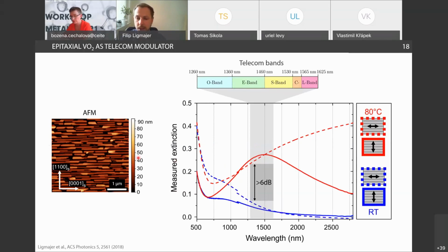And of course, as this material is anisotropic, it will be polarization sensitive. And this is exactly what you see on this graph. So again, we measured extinction by combining various detectors and light sources in an FTIR microscope and spectrometer. You see that at room temperature there is basically very weak dependence on polarization, that is the solid line and dashed line, and polarization is denoted by these arrows. In the visible range, there is some non-negligible anisotropy in your films. At near IR and mid IR, the anisotropy gets lost.